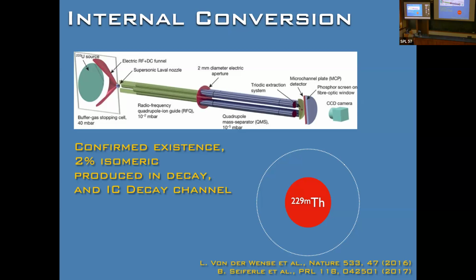When he would do that, the thorium comes off of this uranium as an ion because as it screams out of the uranium, electrons get stripped off. When he soft lands it, it neutralizes. Now, when thorium is neutralized, the energy of the nucleus is more energy than it takes to ionize thorium. And so what it does is the nucleus says, hey, electron, you can have this energy, go away. And the electron flies off and the nucleus relaxes. This is called the internal conversion process. We had predicted this would be a few microseconds, and Peter saw exactly that when he went and did it.